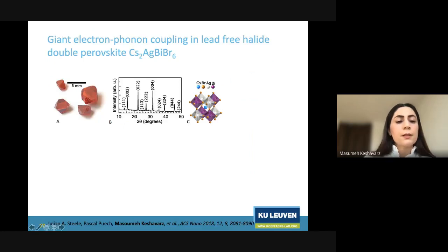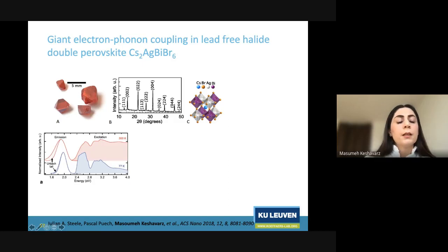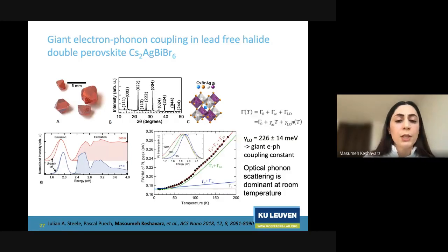So this is how the crystals look. These are the cesium silver bismuth bromide crystals. This is their XRD, and this is their structure, as I explained. Here below in the plot, you see the absorption on the right side and photoluminescence of these materials on the left side, at room temperature on the top and at 77 K at the bottom. As you can see, the photoluminescence at room temperature is much broader because of the scattering of the carriers in the system due to thermal energy.